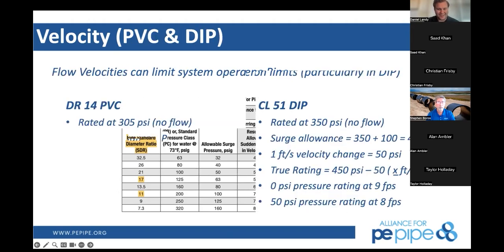Did you have a comment on that as well? Yeah, just to build on that, this is really important because oftentimes we see engineers selecting thicker pieces of pipe to accommodate a greater degree of safety. You don't need to do that with polyethylene, period. Particularly if you want a 1-to-2 safety factor ratio in your designs. In fact, before you commission the polyethylene pipeline, there's a spec, I forgot the name of it, Dan, but you actually test it to 1.5 times its max working pressure before you commission your polyethylene pipeline. So you're already testing that recurring surge limit before you're operating it. Absolutely. We'll cover that in the pressure testing section as well. That's a good distinction to make. Thank you for answering another one of my questions.